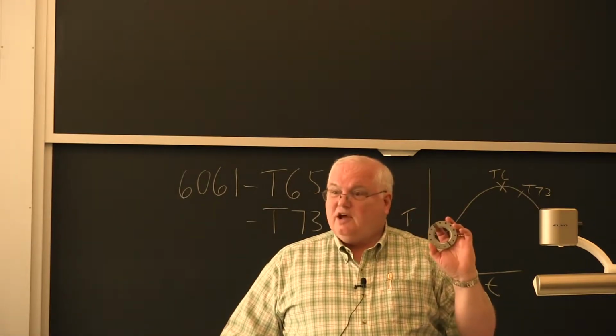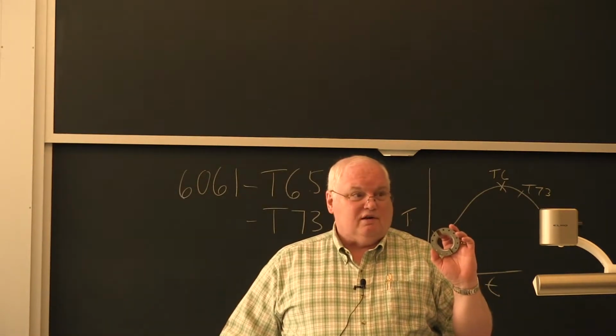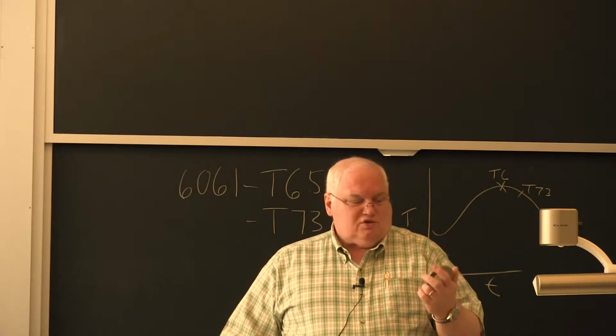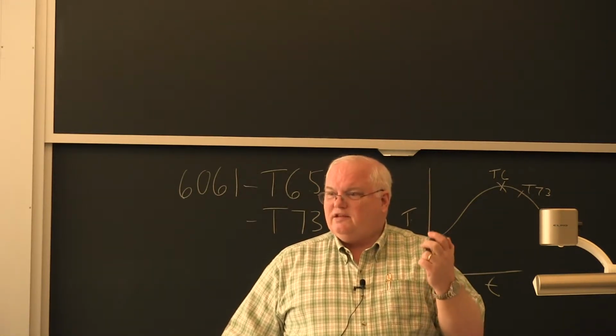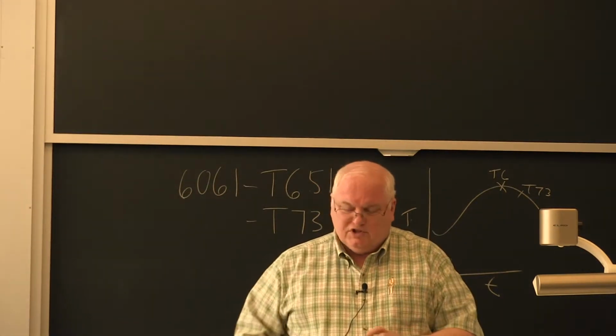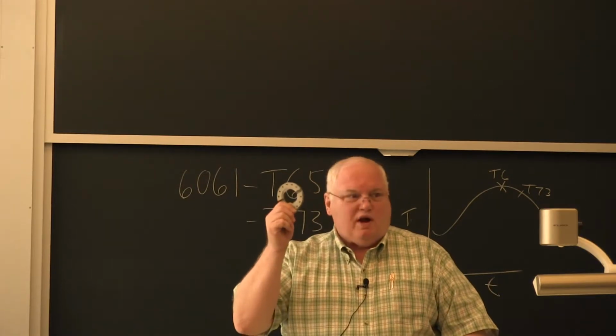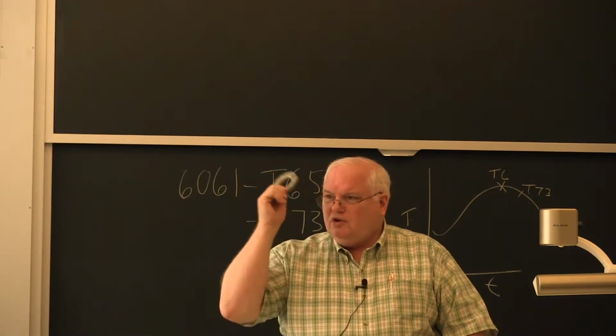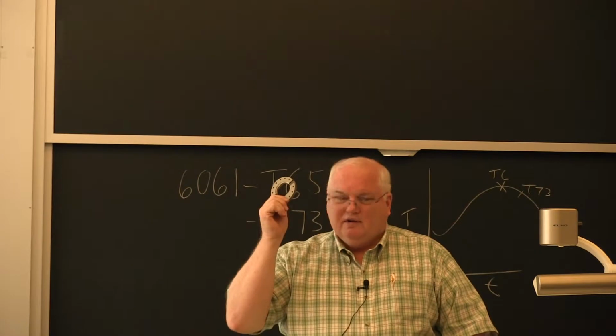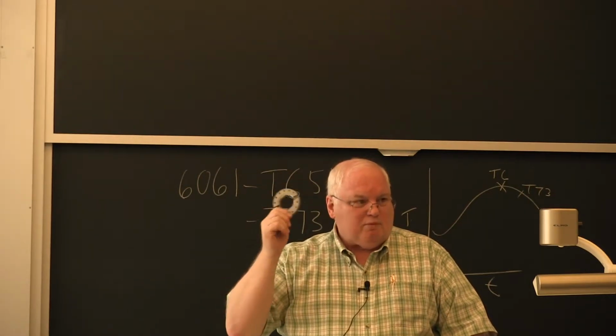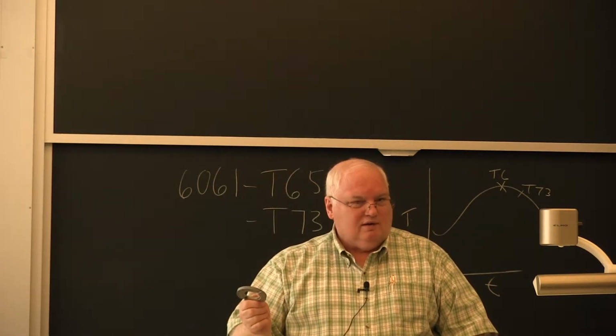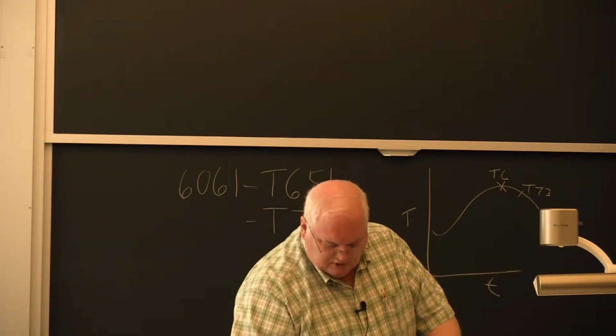Turns out 5 KSI is the stress corrosion cracking limit. So the residual stresses were enough to crack this thing on the shelf without ever putting it in service. The Navy saw it first. Why? Because the Navy is the corrosion leader in the military. They put everything they've got and surround it by salt water, okay? And so the Navy will crack things first.